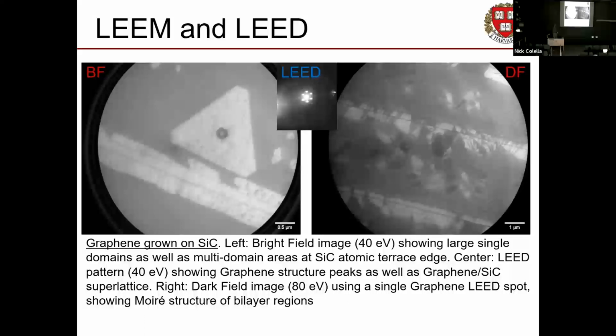And you can see this single monolayer of graphene, but you can not only see it, you can see all the little point defects in it where it hasn't grown beautifully. They show up as contrast as well. You can also take a diffraction pattern off it. Here is the diffraction pattern of graphene growing on silicon carbide. And again, this is a diffraction pattern from a single monolayer of atoms, which, if you know the physics of diffraction, is kind of head-scratchery, but it works. Yay.